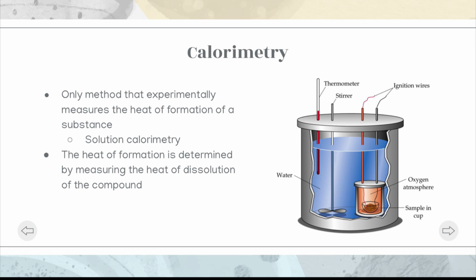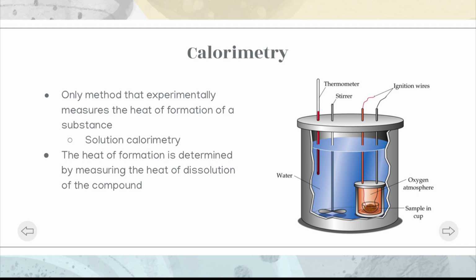Thanks for that wonderful introduction, Christina. Now, it's my turn to introduce you all to the method we intend on using to determine the lattice energy of KCl. To reiterate a few key points that Christina mentioned during the very beginning of this presentation, it's impossible to experimentally determine the lattice energy of a substance. This is due to the relative difficulty associated with isolating ionic species. Though we can't directly determine the lattice energy of KCl, we can indirectly determine it using the Born-Haber cycle. This is achieved by determining the enthalpy of formation of a given ionic species, in our case, KCl.